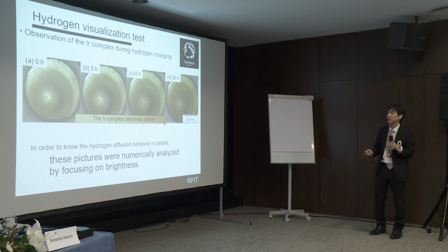And these are pictures of the iridium complex during hydrogen charging for 0 hours, 3 hours, 6 hours, and 20 hours, respectively. As shown in the previous slide, the iridium complex becomes dark, and we can say that the iridium complex successfully reacted with hydrogen permeated through the specimen.